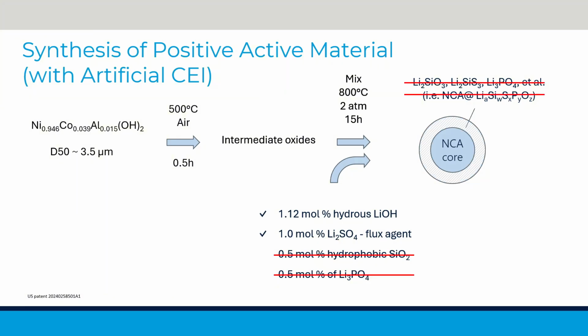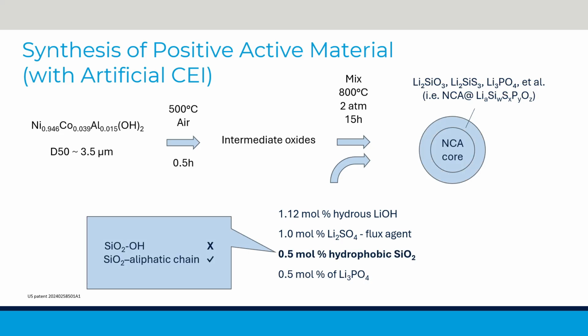It's mentioned that there is a synergetic relation between the flux agent and silica. If only sulfate-based flux agent is used, sulfur does not remain on the surface, and there is no protective layer on the particle. Another note is that the product made from hydrophobic silica performs better than that from hydrophilic silica.